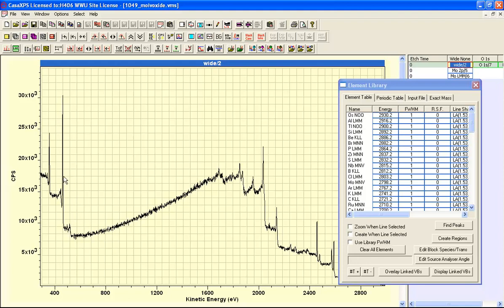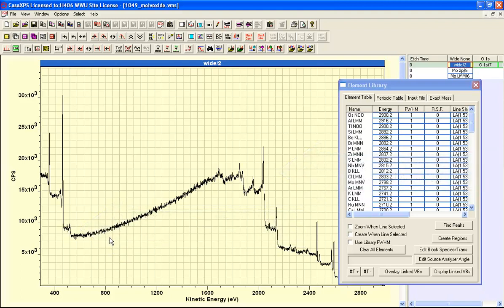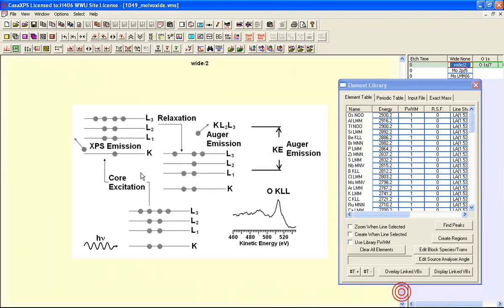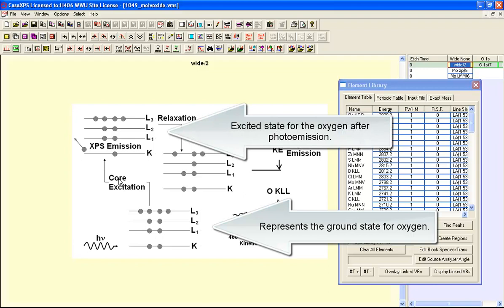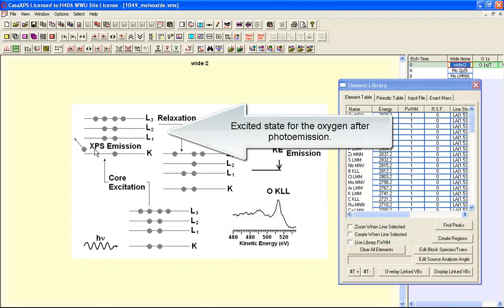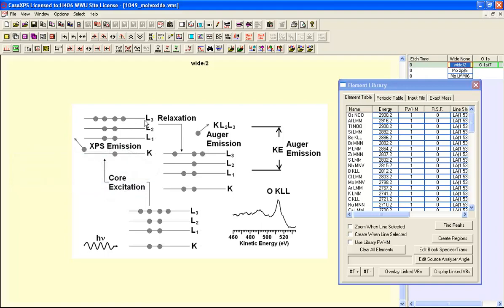The relative position of photoemission peaks changes with the X-ray source in terms of kinetic energy but the Auger transitions are always at the same kinetic energy. The reason for this is because when the atoms are excited by a photon of any energy then the result is an excited state and the emission of an electron with an energy that is characteristic of the photon energy. But the excited state then can undergo a transition which will cause a relaxation resulting in a new excited state. The difference between the initial excited state and the relaxed state is emitted as an electron and this Auger electron has an energy which is characteristic of these two internal states within the excited atom and is independent of the photon energy.